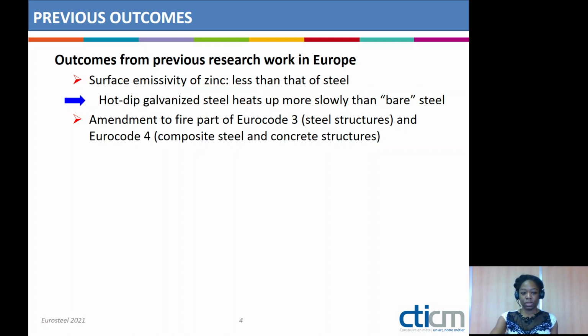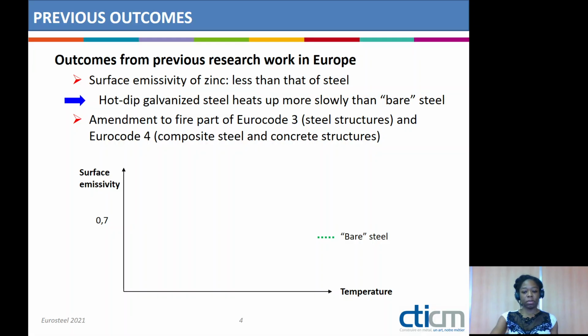This led to a proposal of an amendment to the fire part of Eurocode 3 and Eurocode 4 dedicated to steel structures and composite steel and concrete structures, respectively. According to this amendment, you can consider the surface emissivity of steel members as a function of the temperature. Actually, if you consider bare steel, so without any hot dip galvanizing, you should consider a constant value of 0.7 regardless of the temperature values.